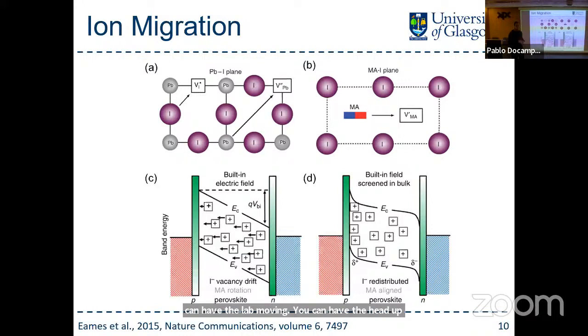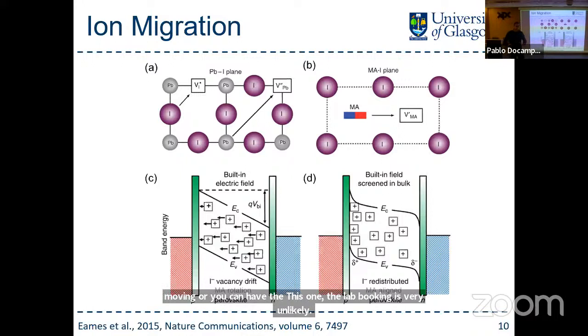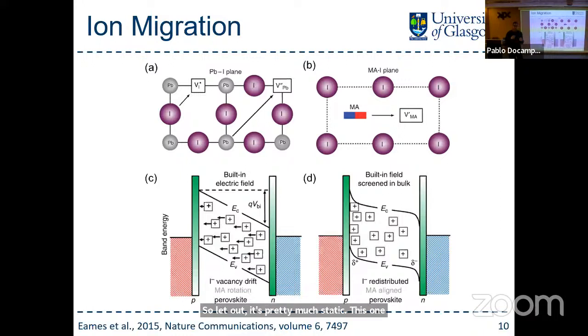The lead moving is very unlikely. It's got an activation energy of 2 eV. That's very unlikely to happen, so the lead atoms are pretty much static. The organic cation can move, but very slowly, in the range of hours to weeks. Whereas the one that is quite mobile is the halide vacancy. This is what we normally talk about when we talk about ion migration in perovskites. We're talking about a missing iodide atom or a missing bromide atom. And the thing here is that the population of these vacancies is actually bigger than the electronic charge when we illuminate it with light. So the ionic population dominates the device physics.